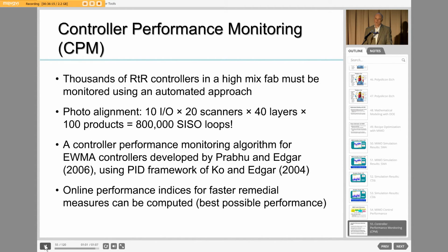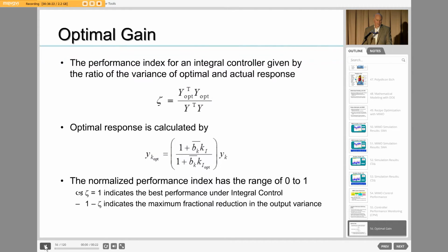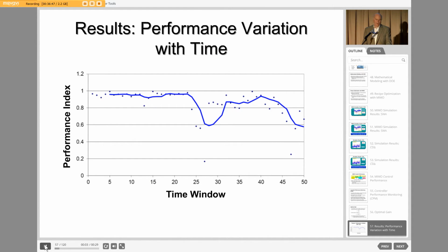We actually had done some work on performance monitoring of PID controllers, and we said, well, hey, integral control, we should be able to come up with something simple here, and so we did that. This is just to give you an idea about a few equations that are involved. The whole idea is that zeta is essentially a measure of how well you're doing. The closer you are to 1, the closer you are to optimal performance, which would be essentially minimum variance. And if you're less than 1, that means you're not performing as well. So here you see an idea of what happened over a period of time in terms of performance variation with a particular piece of equipment. You can see that the blue line is really a kind of curve fit of the whole thing.